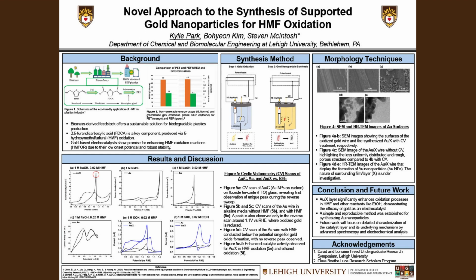This layer was made sure to be uniformly distributed, so 5 CV cycles were run at a scan rate of 10 millivolts per second over a range of 0.4 to 1.4 volts versus RHE. Scanning electron microscopy, SEM, and high-resolution transmission electron microscopy, HRTEM, were used to examine the morphology of the gold wires from steps 1 and 2 of the synthesis method. Figure 4a and b show the final results of steps 1 and 2 respectively. The CV for the oxidized gold wire resulted in uniform distribution of AuX particles.